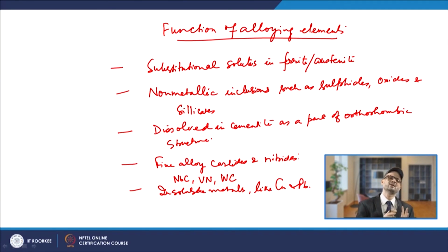And then more importantly, these carbides or nitrides, or some carbides like molybdenum carbide or vanadium carbide, are enhancing the creep strength. Some of the carbides also increase the wear resistance or abrasion resistance. So, these are typically the effects of these alloying elements, and their effect is also there towards the hardenability of the steel, from where we can get the full hardening of the steel, the martensitic structure or so.